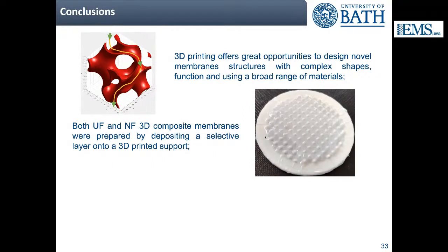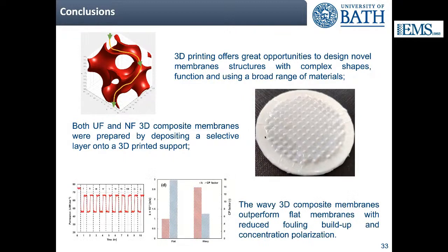However, there are limitations, and by working around and with these, we were able to fabricate both ultrafiltration and nanofiltration composite membranes by depositing a selective layer onto a 3D printed support. And the wavy structure significantly outperforms flat membranes with reduced fouling buildup and reduced concentration polarization when you go to the NF region and charged probe particles.